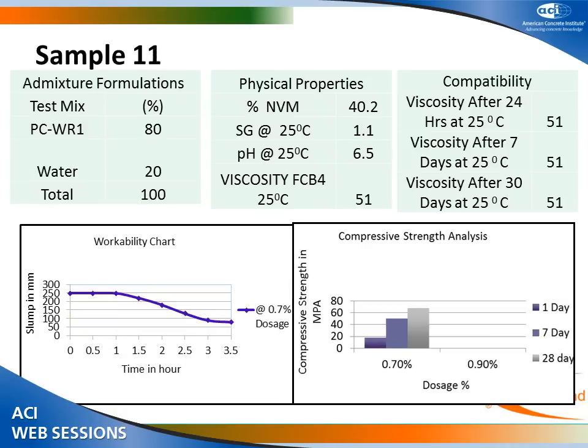Sample 11, again this was a pure PC, WR1. We wanted to see the performance of WR1 against the combination as well as the combination of slump retention type PC. And here again we get good slump retention at 0.7% dosages. The strengths are around